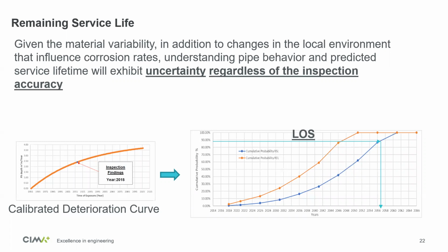What we actually did is, because this model offers a range of parameters to use, we calibrated this model using actual inspection results, and therefore we calibrated the parameters better, and now we have a more representative deterioration curve. One important fact when we do the remaining service life is there are always uncertainties.